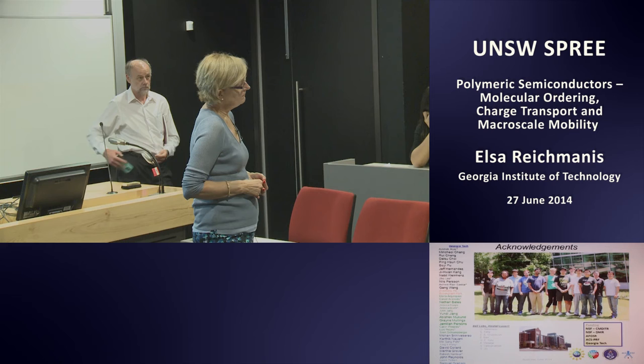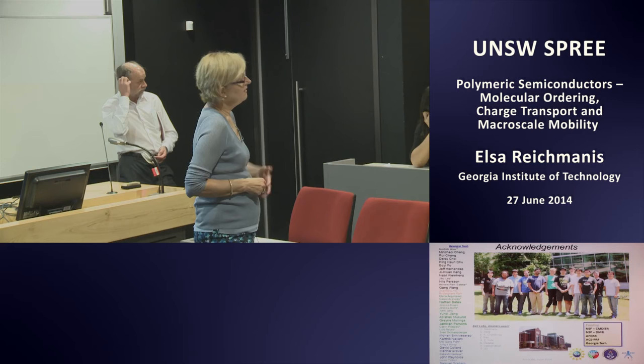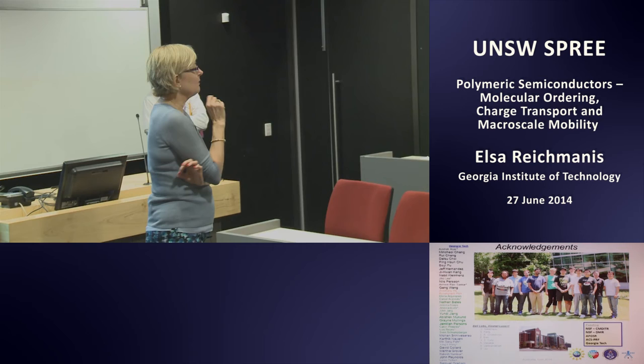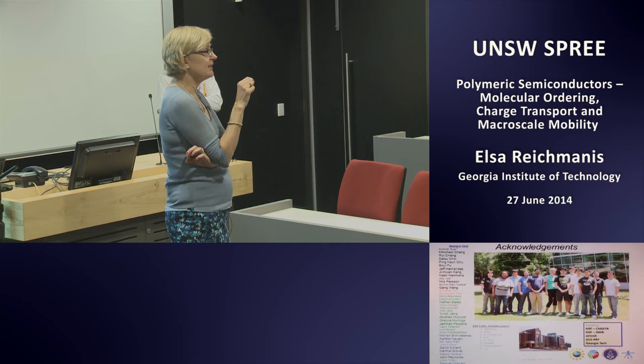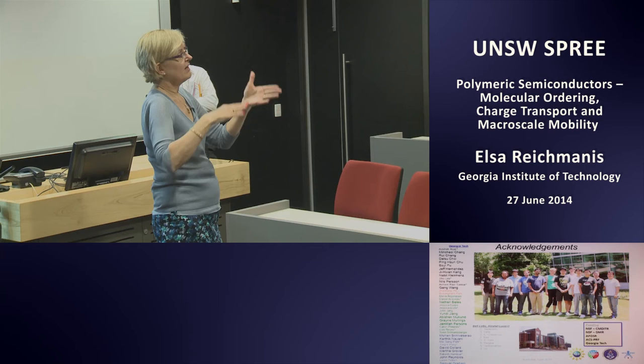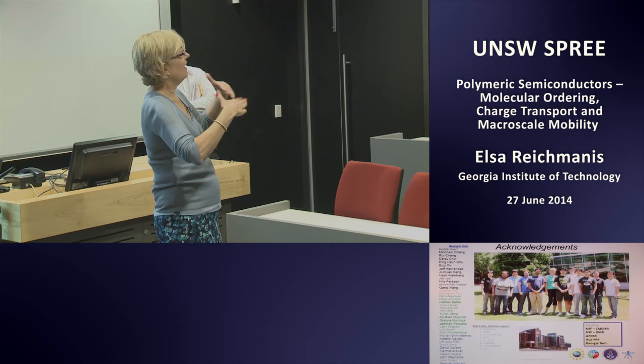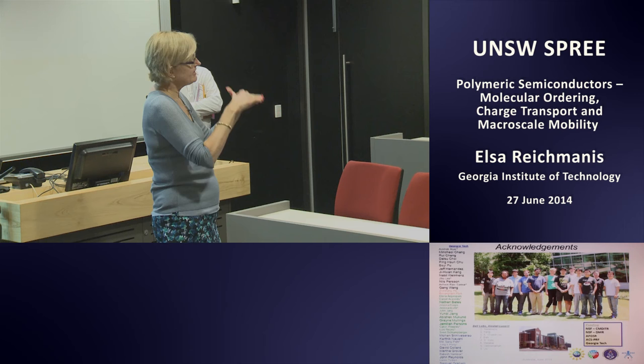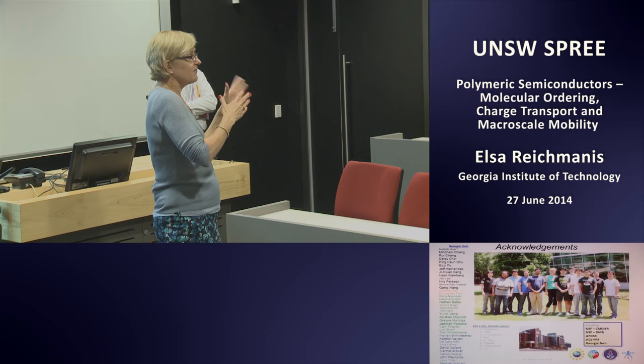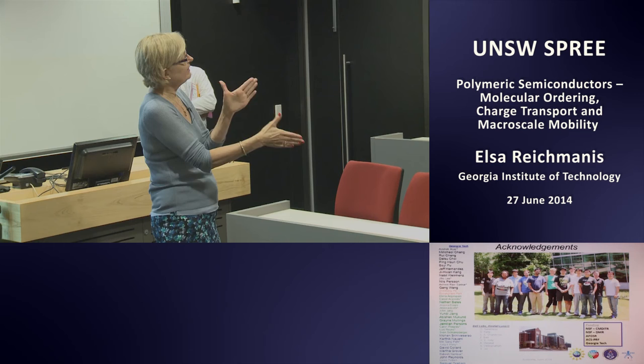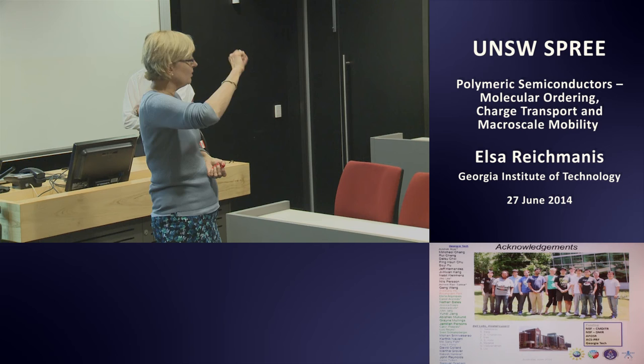Now, perpendicular orientation is good for the transistor, right. Not good for the solar cell. For a solar cell we want parallel orientation. Is it possible to control the orientation? We believe it will be possible, but we have not looked into it, because it is possible to control the polymer orientation by changing the characteristics, the polarity, of the substrate surface. So I think through treatments of the substrate with a self-assembled monolayer, which would have to be experimentally determined, it should be possible to affect the orientation.